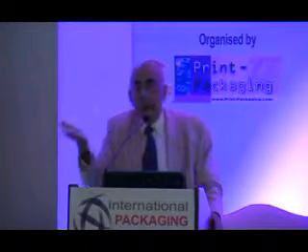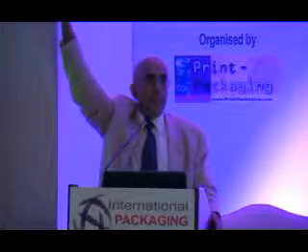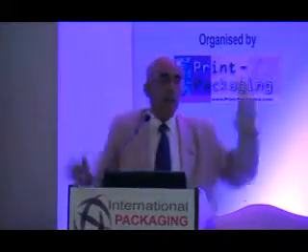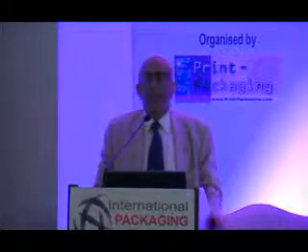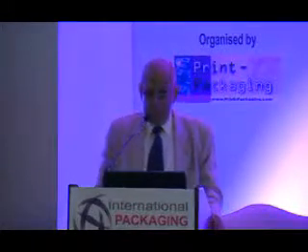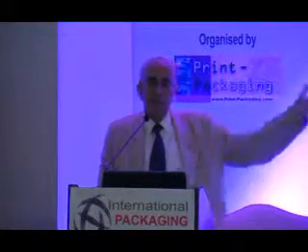All of them require 90+% of the carbon be consumed by the microorganisms as measured by the evolved CO2. And if you don't have that, you should not claim it is biodegradable. You should not sell it as biodegradable because people believe so, and therefore you're causing more harm than good. And I'll show you that in a minute.